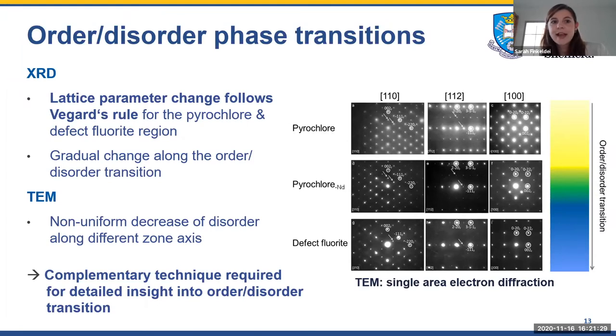So basically, Vegard's rule, which I mentioned here. Vegard's rule predicts that whenever we have a solid solution, there is a linear dependence of the lattice parameter on the chemical composition of the solid solution. And we can probably see that a little bit later on another slide as well.